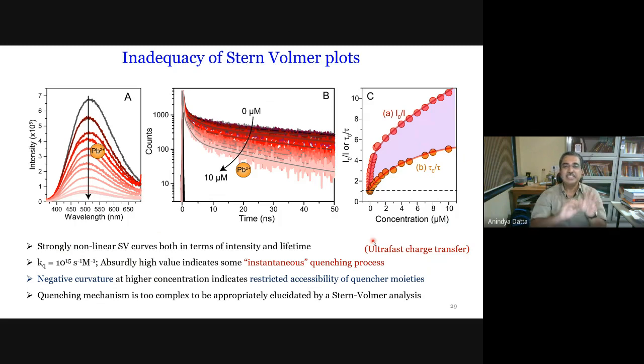This is an analysis that we did reluctantly because we knew it doesn't work, but then one of our reviewers insisted that we do it, and well, finally we could make a statement out of this. Whenever we see quenching, the classical approach is to construct Stern-Volmer plots. The issue is that the Stern-Volmer plots are very, very nonlinear. The plots that we get using steady state PL intensity and lifetime are very different, and the quenching is too strong. X-axis here is in micromolar.